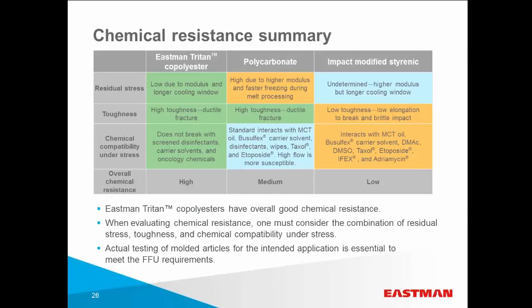So, chemical resistance summary. We recognize that residual stress is one of the drivers of chemical attack. Tritan copolyester has lower residual stress. It's related to the modulus and the glass transition temperature, and the longer cooling window. Polycarbonate always has a higher modulus and higher residual stress. And typically most molders that run polycarbonate recognize you either have to slow down the process and use a hotter mold, which would increase the cycle time, or you have to do secondary annealing to help reduce some of that stress.